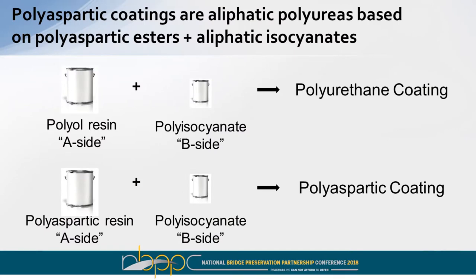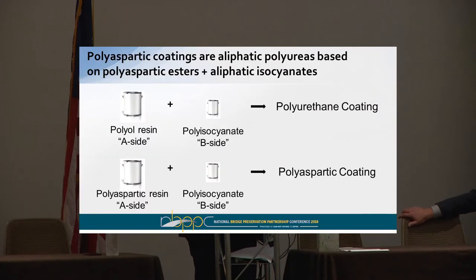So what are these polyaspartic coatings? Well, they're very similar to standard polyurethanes in many ways. Both polyurethanes and polyaspartic coatings are two-component systems where you've got an A side and B side that are mixed right before application. Now, what really differentiates them is on the A side of the polyurethane, you've got a hydroxyl-bearing polyol, which is either acrylic or polyester-based, and that reacts with the B side, which is a polyisocyanate, or catalyst or hardener, however you want to refer to it. And that reaction results in your polyurethane coating.